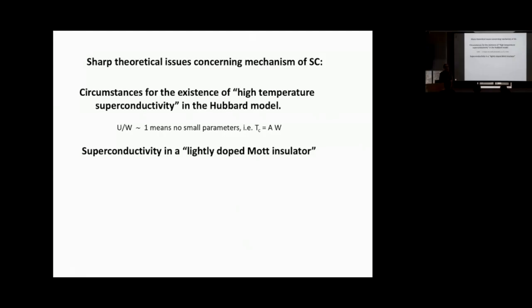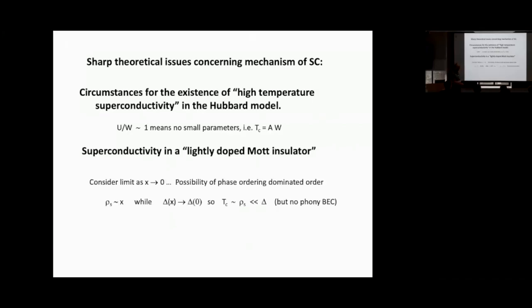And then one other issue is, can we get superconductivity in a lightly doped Mott insulator? That is to say, can we find a case where we find superconductivity that persists as the doping concentration goes to 0, and at the same time, this would suggest that maybe we'll find a regime where the superfluid density is parametrically small in proportion to the doping concentration, while the pairing scale is somehow inherited from the insulating phase, so that one will get into this interesting regime, which does seem to be observed in the cuprates, where Tc is of order the superfluid density, and the pairing scale is larger than Tc, and not anything to do with Bose-Einstein condensation.